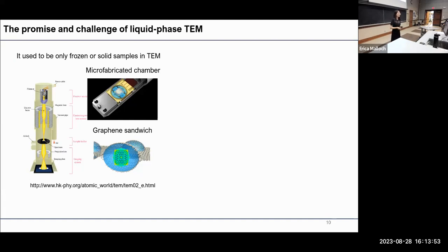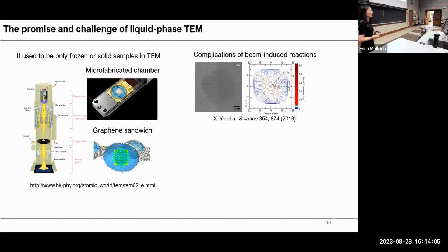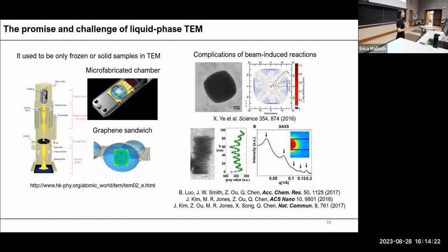As I talk about electron beam effect, this is all because the electron beam has high energy. If you are taking a continuous movie, that also means you are showering your electron beam continuously on your sample. And sometimes that can fundamentally change the nature of the sample, as shown here. You can use the electron beam to induce the corrosion of gold nanoparticles in a graphene liquid cell. So that's why the first few papers in my group really try to do a few beautiful control experiments to identify the good electron beam intensity, or electron dose-rate regime, within which we do not need to worry about electron beam effects.